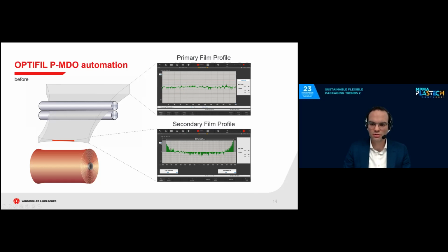And when you stretch this film, it gets thinner and narrower at the same time, just like a rubber band that you would stretch. You can also see this in the secondary film profile after stretching, the picture on the bottom right. You can wind this film, or at least you can try, but the edge buildup would cause defects in the film, making it impossible to process downstream. Here, you would have to cut away a lot of film in the edges, creating a lot of plastic waste and losing machine productivity. So how can we combat this phenomenon?